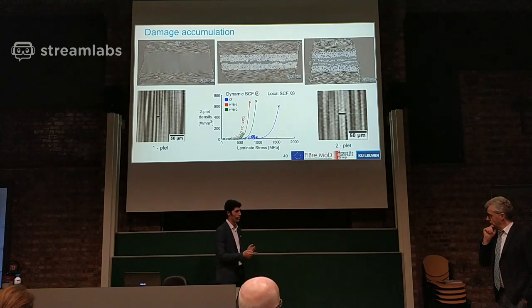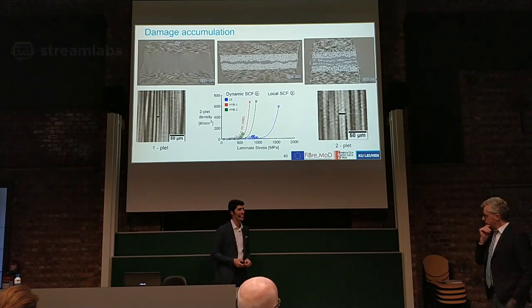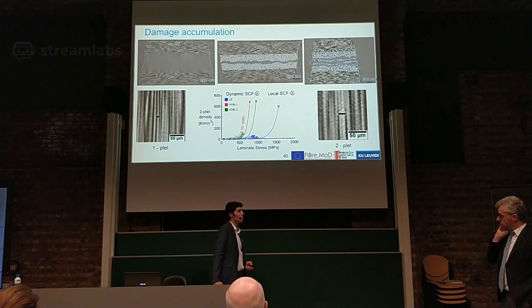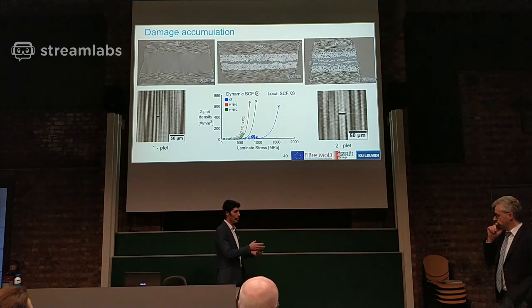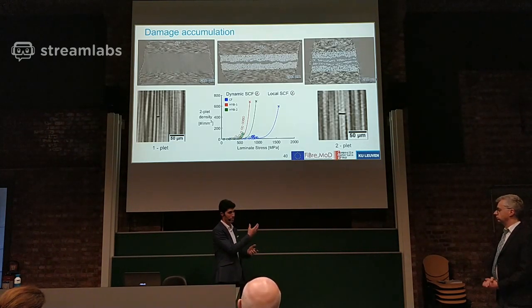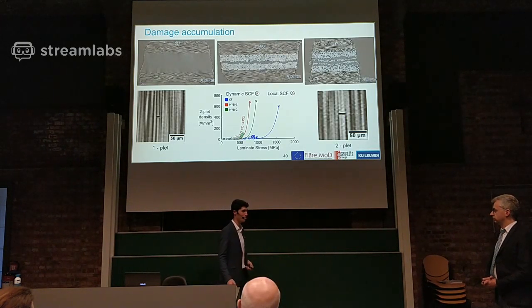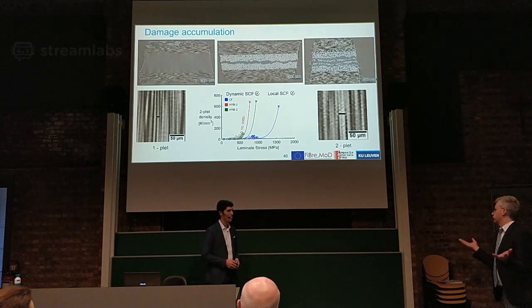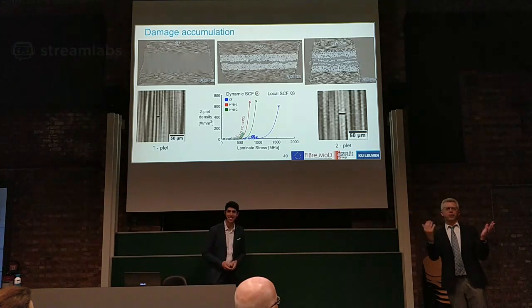Concerning the interface, you mean surface flaws, or the interface as in debonding? Surface structure, roughness to start with, maybe. Yeah. For the local stress concentrations, I don't know exactly how that would play a role, but indeed the surface of the fiber could play a role in debonding. When the fiber breaks, it will debond from the rest of the matrix, transferring the stress concentration not to the fracture surface plane but to another region, and break fibers that are weaker but not exactly there. Again, I think the more detail we add to these things, the better we will get in general. Yeah, of course, it's always a trade-off with the computation. Exactly. Okay. Any questions from the audience?